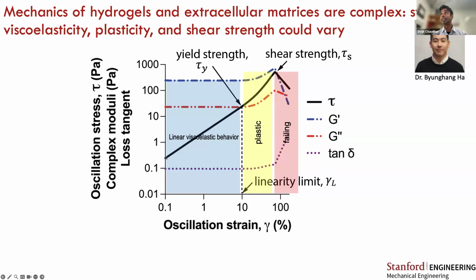We see initially there's a linear relationship between the two. So this is the linear viscoelastic range where we can get a storage or elastic modulus as well as a loss or viscous modulus. At a certain point, the material starts to undergo plastic deformation, at a yield strength. And we enter a regime known as the plastic regime, where the material undergoes plastic deformation. And finally, at some stress, which in a shear test would be the shear strength, the material undergoes failure.